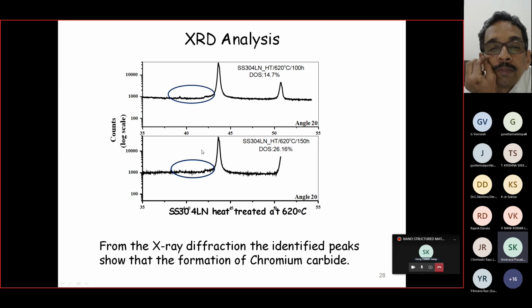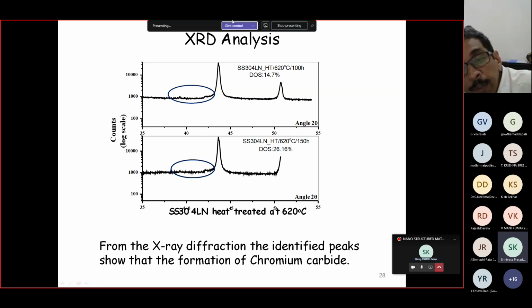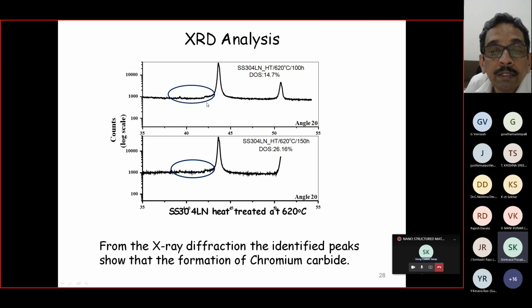Even though at a very high magnification you are seeing it is quite large, if I go to the bulk of the material, it is very, very small. So I can see some small changes over here, but this is not very significant. These are all the austenitic peaks of the stainless steel. Compared to that, these ferromagnetic peaks are very, very small. So whenever we are thinking of an experimental technique for characterization, we should also know the limitations of the technique. In nanoscience and technology, X-ray diffraction may or may not be able to give us much information. This is what I wanted to show through this slide: with X-ray diffraction we are getting a slight change, but it is not very clearly visible to us. So try to understand that X-ray has a limitation.